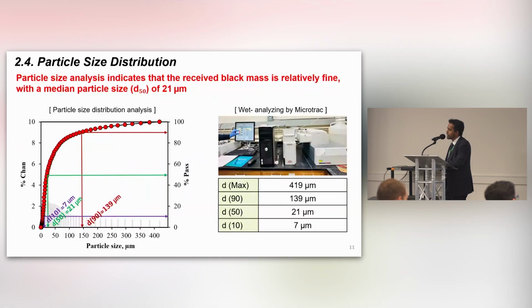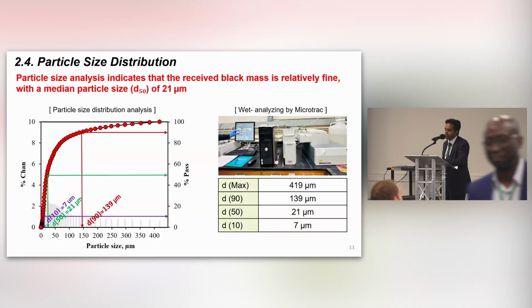We also measured the particle size using wet analysis methods using the Microtrac, and we identified that our black mass is mostly under 140 micrometers.